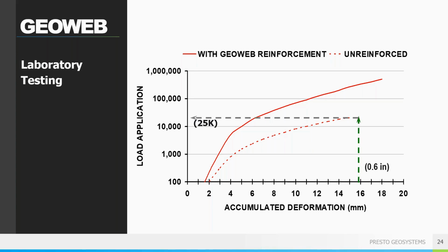We can see that without the GeoWeb in the section, it took 25,000 load cycles to get to this failure point. By adding GeoWeb, we were able to achieve 400,000 load cycles. So an improvement of 16 times the number of load cycles for the very same deformation.